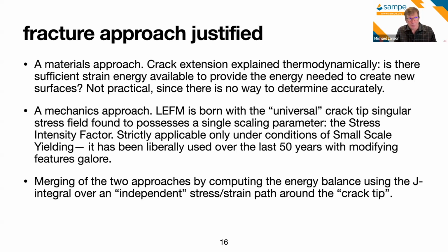And with this universal solution, we observed that it's scaled with a single parameter that we call the stress intensity factor. So the stress intensity factor doesn't give us the stress at a crack tip, since that's always infinite, but it does scale how quickly one gets to infinity is a way of thinking about that parameter. And having done real stress analysis, I was shocked at how people took that very simple yet powerful concept, but then start applying it everywhere, even when it didn't strictly apply. And as a consequence, we have had, last count, I think it was a gazillion ways of modifying that basic solution found for small scale yielding conditions. And it's been used liberally, as I say on the slide, with modifying features galore.